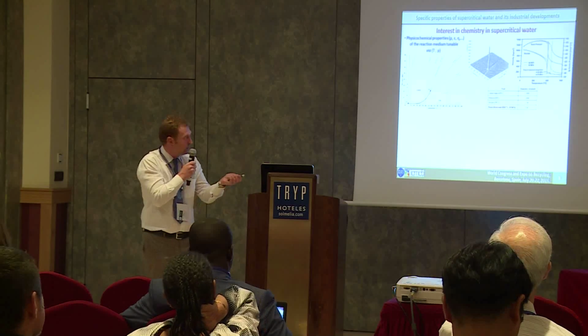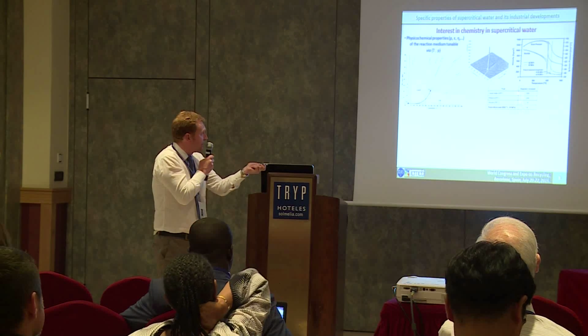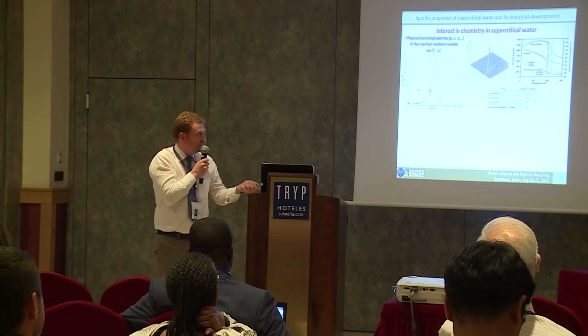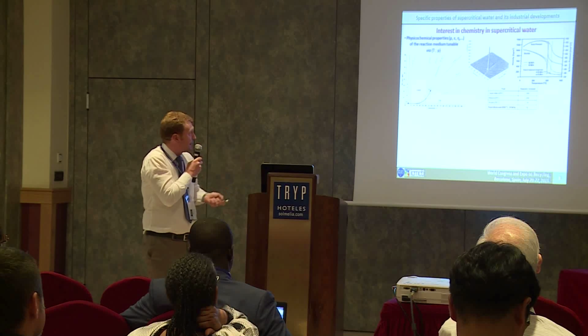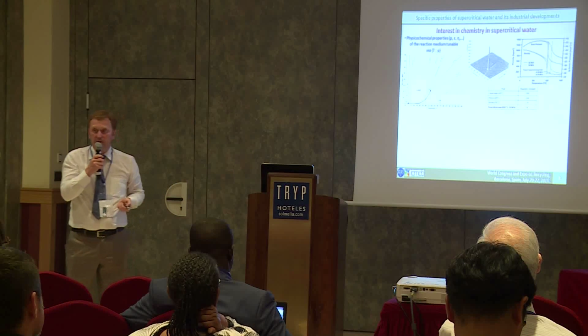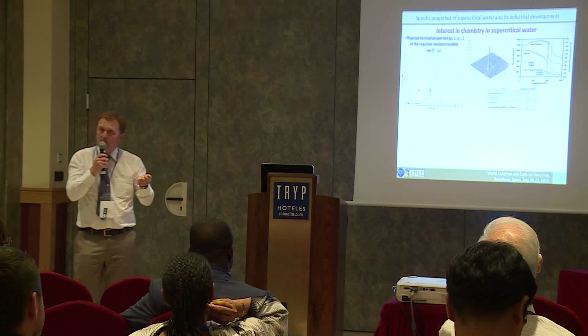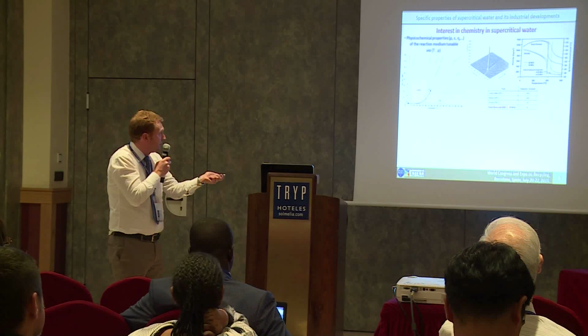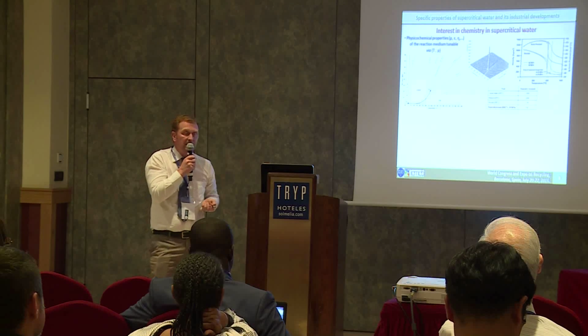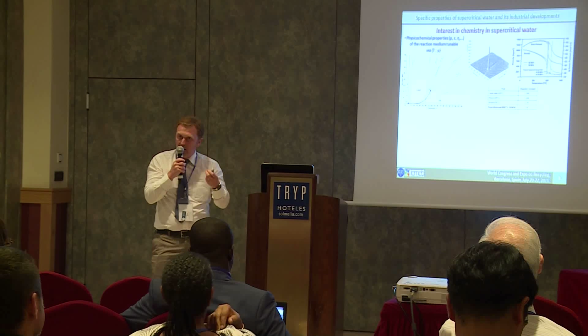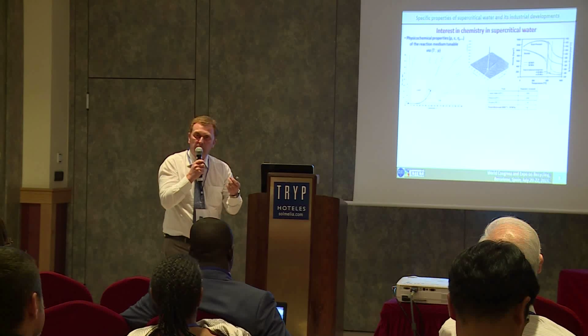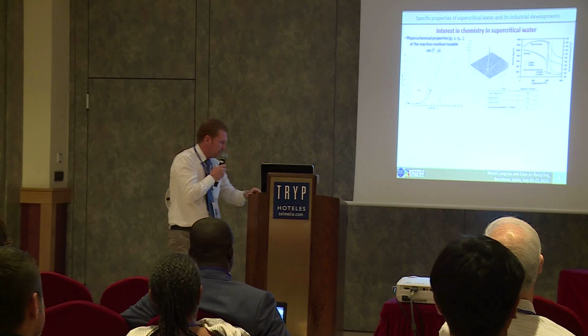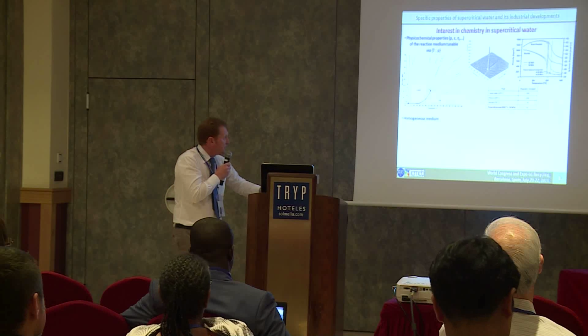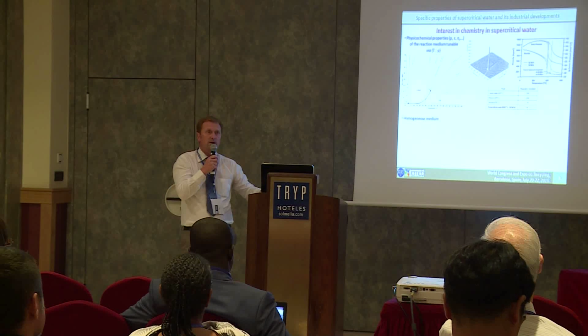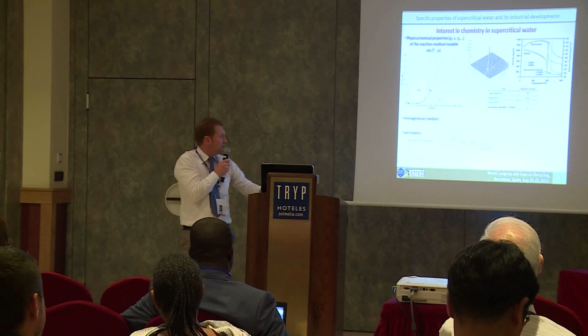And another very important property is the evolution of the dielectric constant. Everybody knows that water is a polar solvent, but under supercritical conditions, you see here, it's a solvent with a polarity like hexane. So this means you can solubilize some organic molecules in supercritical water. And thanks to these properties, you can perform reactions in homogeneous media.